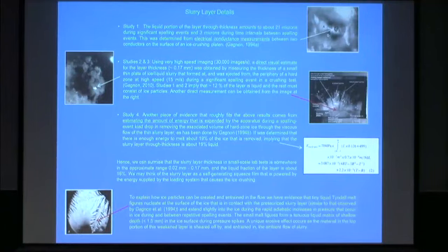So this was from ice experiments where we were hydrostatically compressing small samples of ice and observing melt figures that nucleated at the surface and propagated into the ice. A melt figure is a negative crystal, if you like. It's basically a liquid-filled, sort of faceted type structure. Looks like fern. But these will grow as a function of the amount of superheating that one applies.